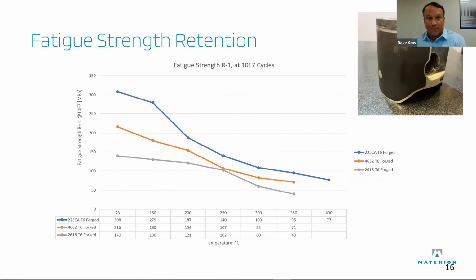So this is rotating beam fatigue. You've got a rod that's spinning and you're just pulling the rod downward as it spins. So that is fully reversing, so the rod is bending by rotating, in all directions, in a circle. So it is fully reversible fatigue. And what this is on the left is the stress applied, and sorry for switching units on you, these are MPa now, but the stress applied where it breaks at that temperature at 10 million cycles, right?